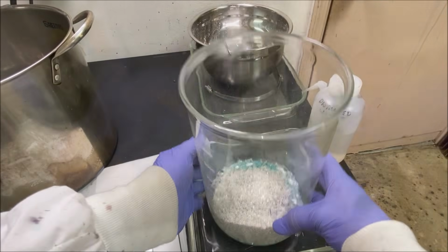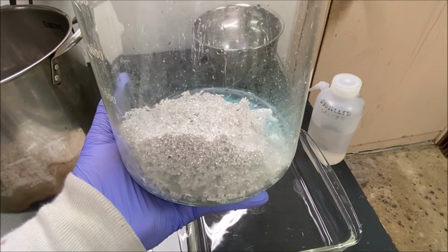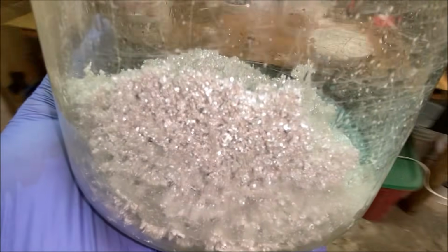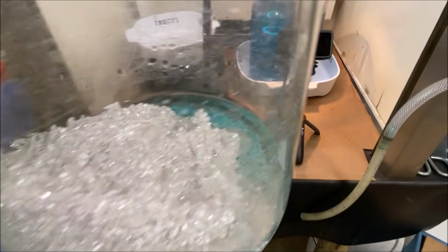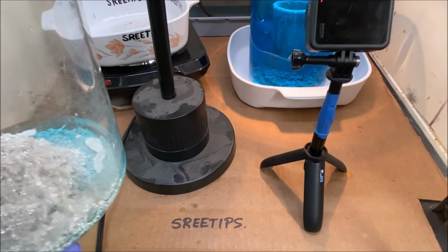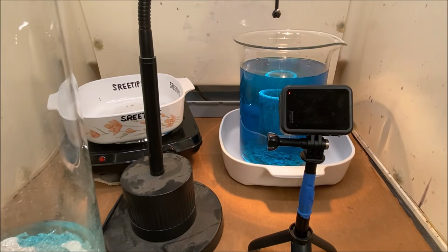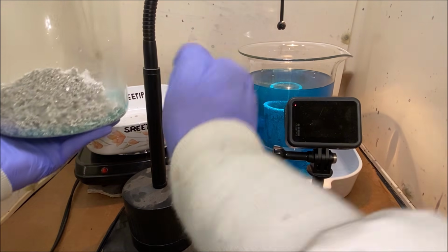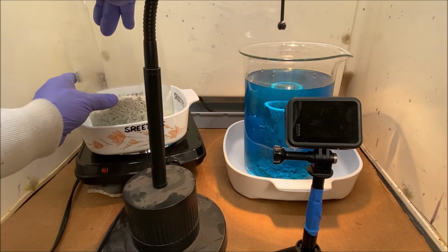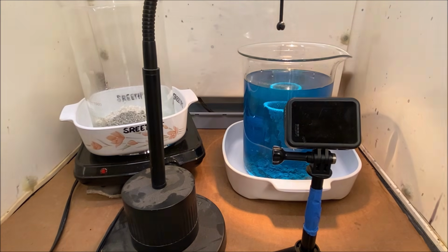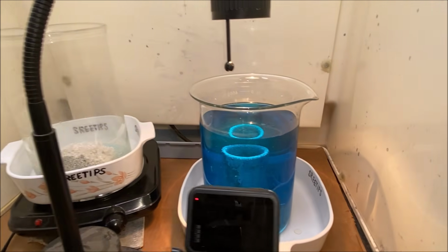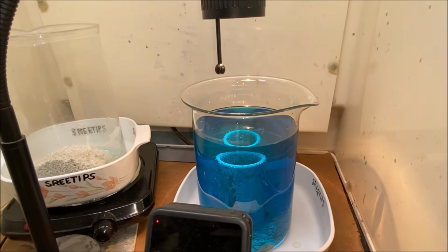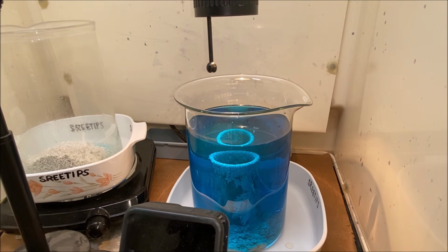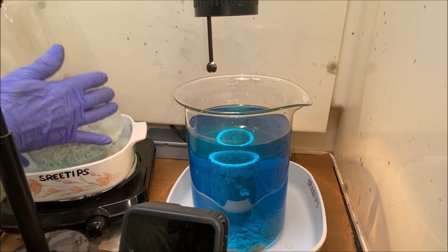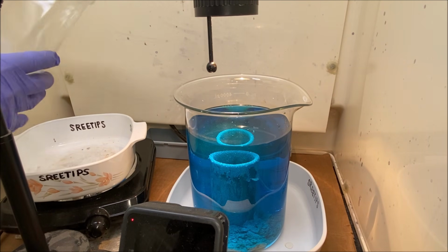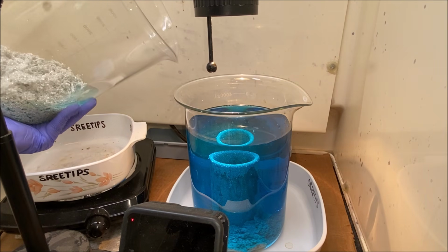That's going to be about 1.5 kilos of high purity silver. So what we'll do is we're going to come over here, that electrolyte in here is high concentration electrolyte, has silver in it still. So let's see if we can pour it into this beaker back here where we're cementing our electrolyte without disturbing the shot that I've got set up.